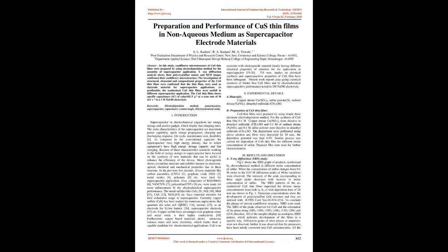The CuS thin films show specific capacitance of 102 F/g at a scan rate of 10 mV/s in a 1 M NaOH electrolyte.